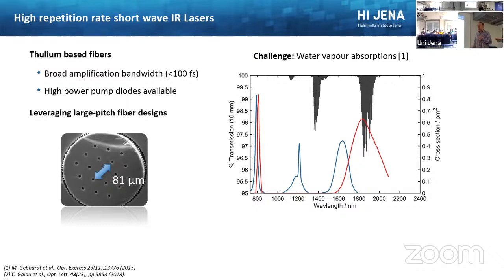Normally, the issue with high harmonic generation is, if you go to lower wavelengths, if you go to 500 nanometers or so, you get a very high efficiency of your HHG process. But you cannot go that far. Normally it's not intuitive, if you're not working in this field, that you start with a longer wavelength and get to a shorter wavelength. But